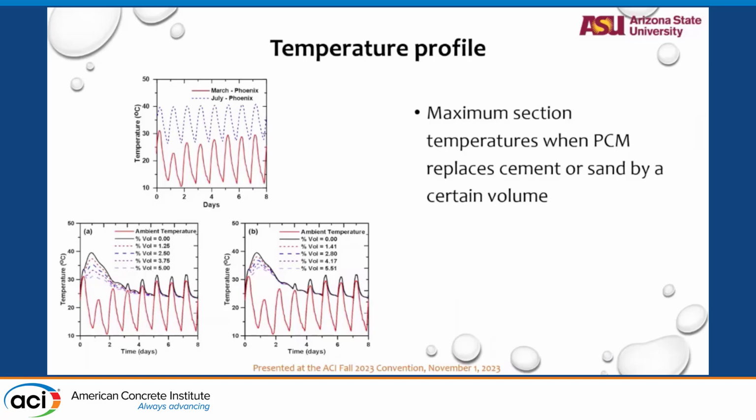Blue is the cooler color, but again the graphs are opposite, it seems. This is now in the range of PCMs that we want to use. When we were working in the lab, we were using 20%, 40% of PCMs just to see the effects. Here the PCMs are in the general range that we will want to use in the field, in the range of 2, 4, 5% by volume.